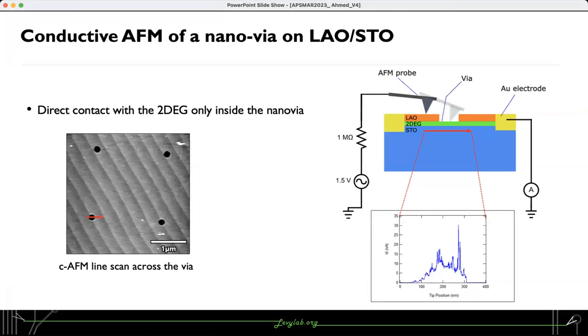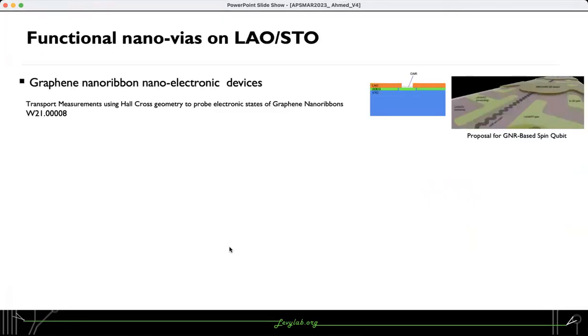The question becomes, are the nanovias small enough to allow for direct contact with the 2DEG? To address this, we use conductive atomic force microscopy. In this experiment, we're sourcing AC voltage from the AFM tip while scanning a line across one of the nanovias. The acquired signal matches the profile of the nanovia, confirming that it's only coming from this region. So how can we make use of these nanovias?